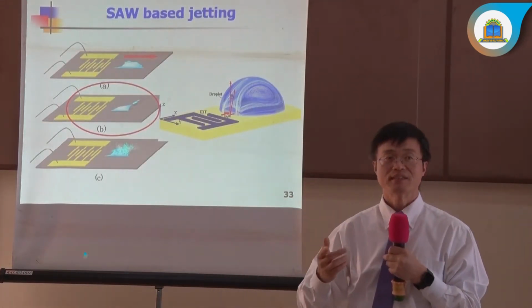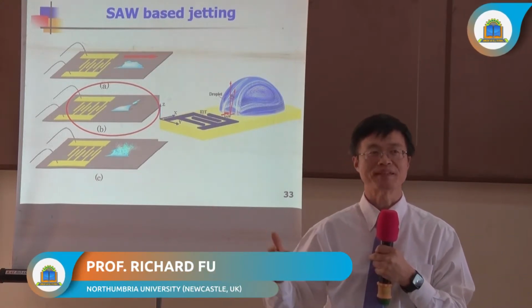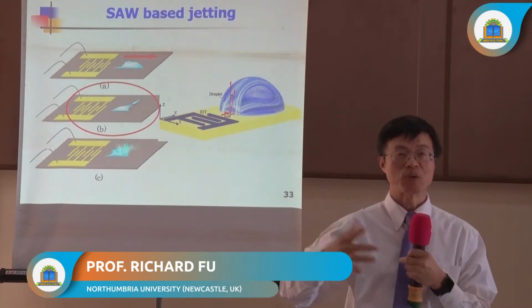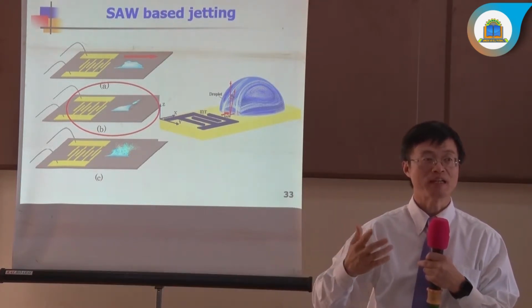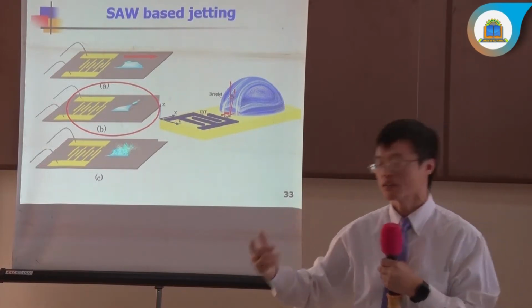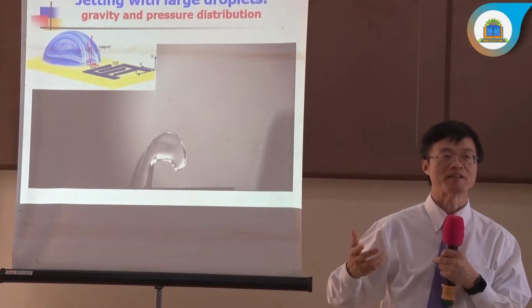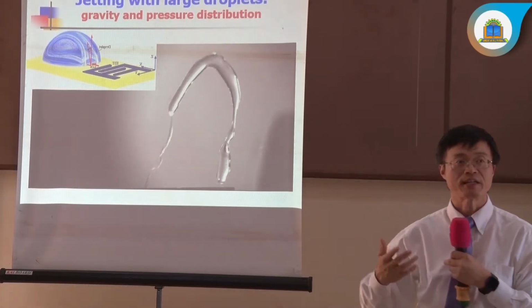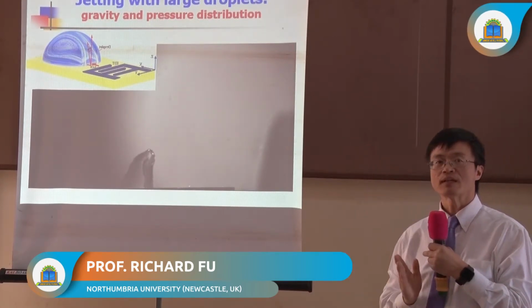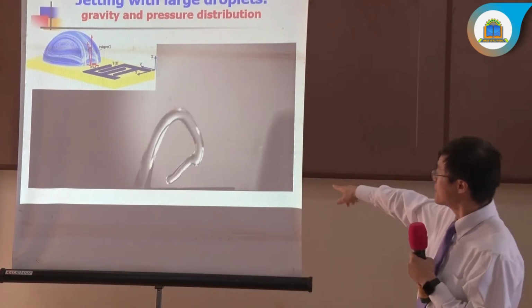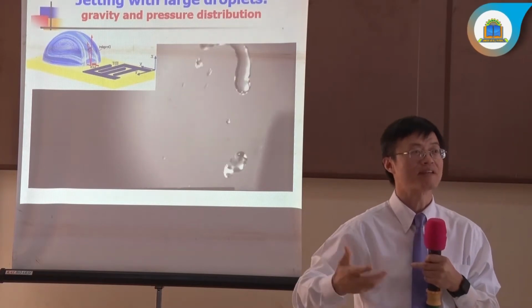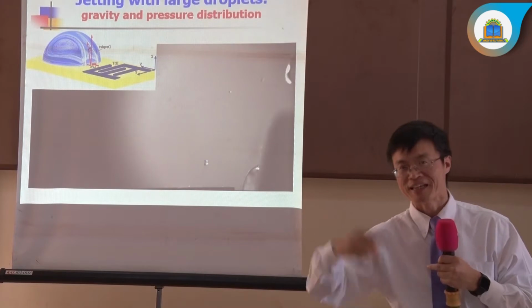Not only here, it's quite easy to form the pumping. What we can do if we increase the power is that the liquid droplet might not have enough time, and it will be ejected from the surface. That means we can do jetting, right? For example, here we have a very large droplet, like 50 microliters. The energy is absorbed by the liquid, and the liquid has high power from the surface wave. It will push up the droplet and eject it like a liquid beam. At the same time, the gravity of the liquid becomes significant because it's huge. Then the droplet wants to fall down, but surface tension holds it up. So all the liquid has been ejected from the surface, right?